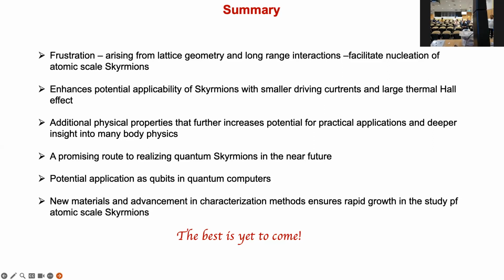So if you have nearest neighbor being ferromagnetic, then this will be your configuration that satisfies all the bonds, right? But now if you have a next nearest neighbor antiferromagnetic interaction, that competes with this ordering. So that is interaction frustration. Okay, and indeed these long range interactions are driven by this RKKY type coupling, which oscillates with distance.